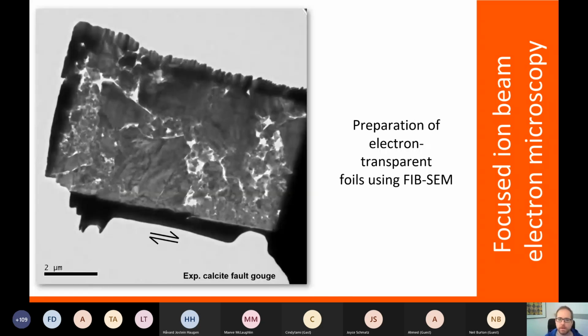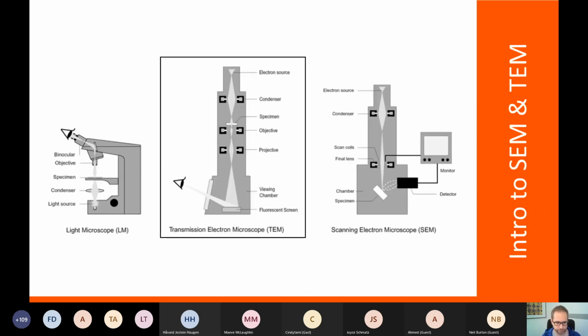So here you see one of these samples in a TEM already, and I will talk about TEM more in a minute. But now the sample is electron transparent. Actually, here on the bottom is the platinum that you see, and a little bit of the needle that has not fully come off is seen here on the left-hand side. But now we have, with focused ion beam electron microscopy, a very powerful technique to extract extremely site-specific samples from anywhere, really, to take it to a transmission electron microscope to observe nanoscale and atomic phenomena.